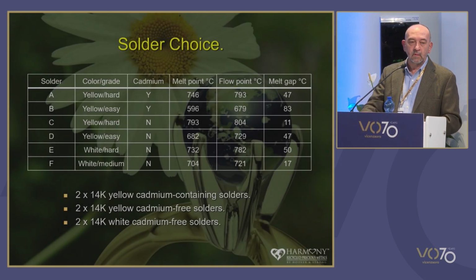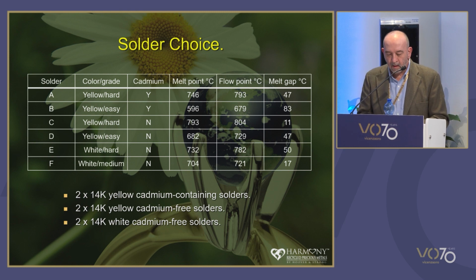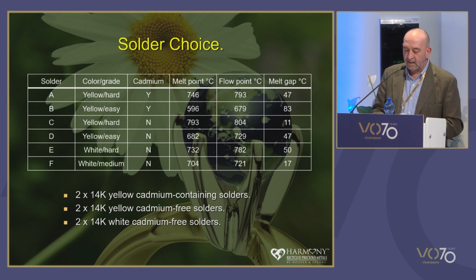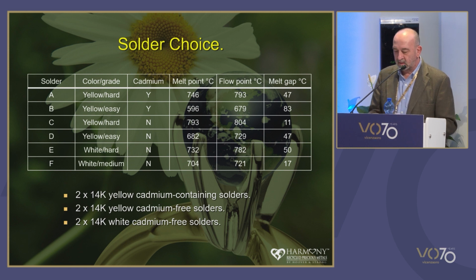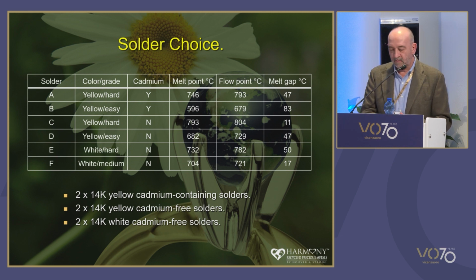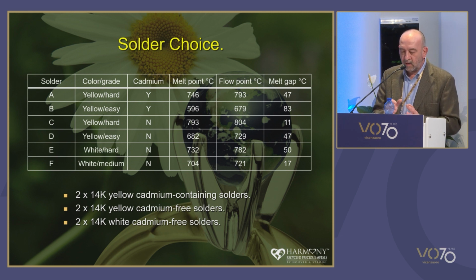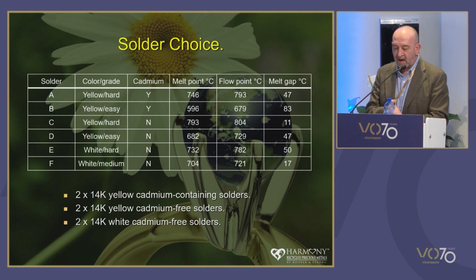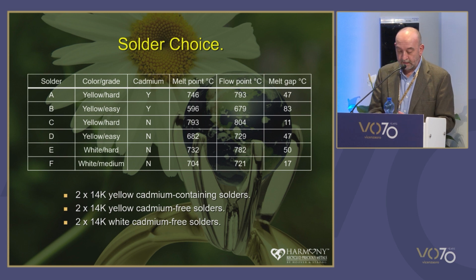So we chose a relatively simple study. We did 2 14 yellow cadmium-containing solders, 2 14 yellow cadmium-free solders, and 2 white cadmium-free solders. And again, as you can see from these melt gaps, the cadmium-free versions do have narrower melting gaps than the equivalent cadmium-containing solders.